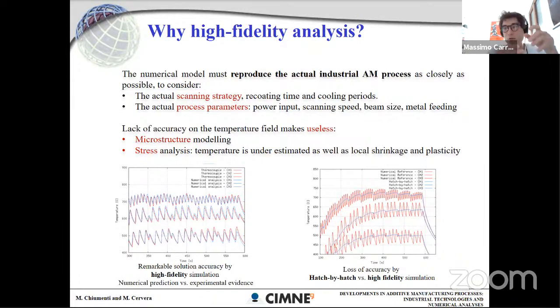And maybe we are not too much interested in what occurs at the very local region around the melt pool, because at the end of the day, that part is almost steady state for a large part of the process. Instead, the accumulated temperature really changes the material microstructure from one part to another. For example, I'm thinking about lattice structures where you see a martensitic region on the skin and a larger cell in the microstructure inside. And this is due to the residual heat that depends on the layer effect and not too much on the local.